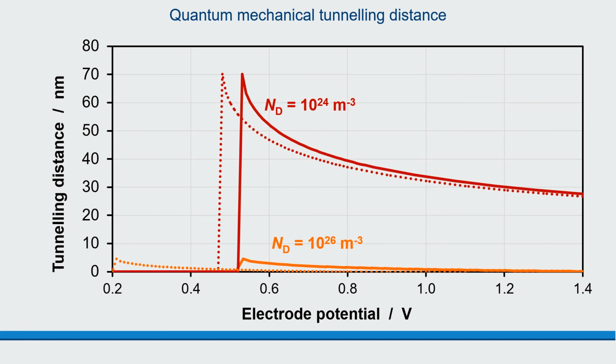It shows that dark currents, for all of the doping levels, are predicted to start much earlier, and this is particularly significant for the highly doped case. But this highlights that the exclusion of the Helmholtz layer results in somewhat unrealistic predictions.